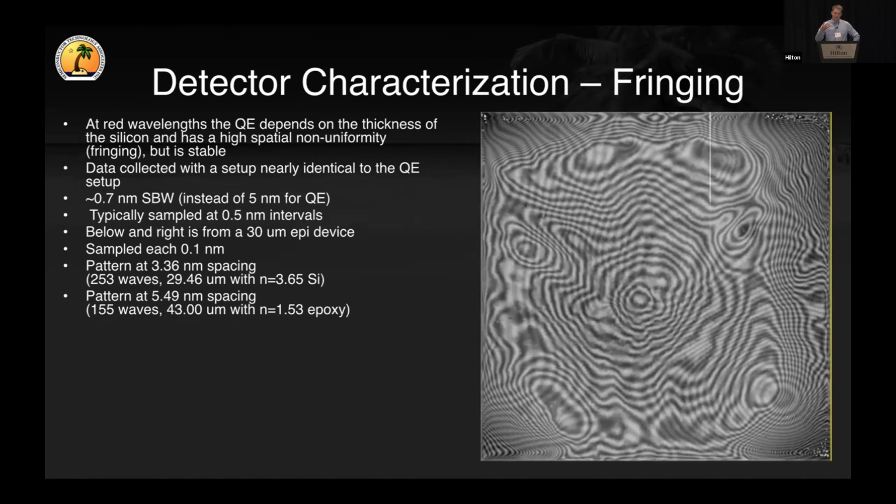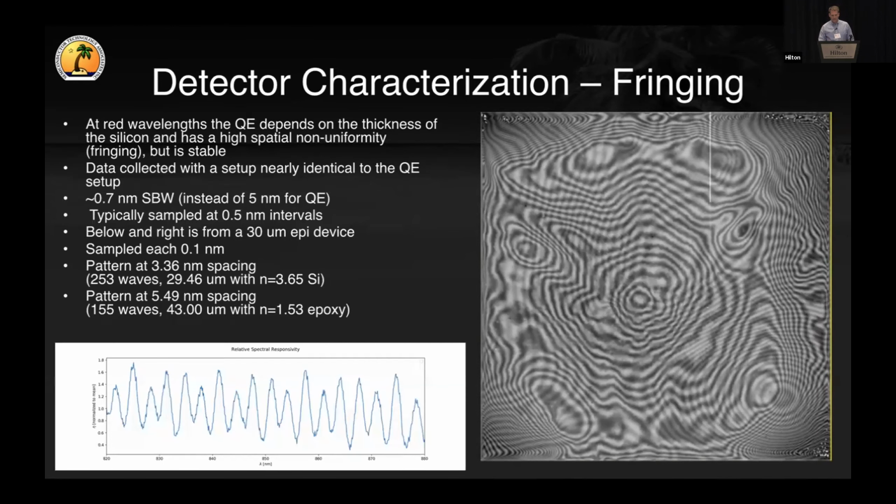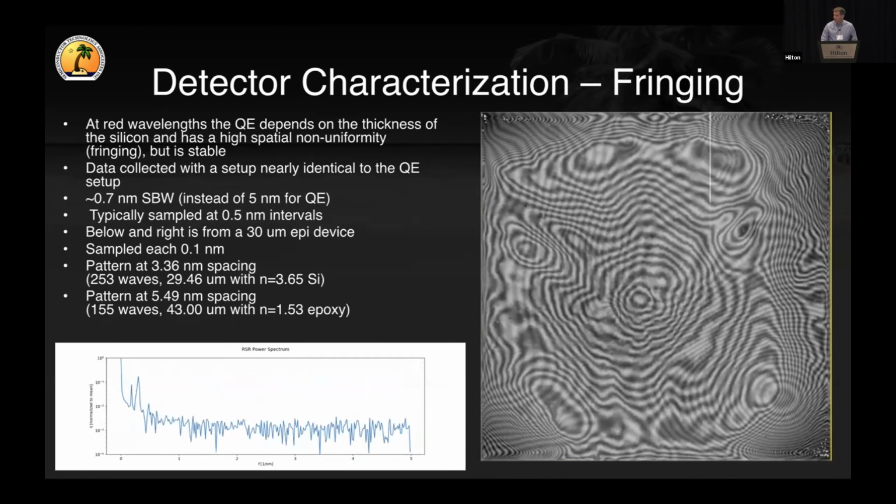And so I can change the fringing pattern and then measure it extremely well, and then measure the thickness of the CCD. Now that's fixed, and so in theory that could be used permanently in data. It doesn't change ever from the time of manufacture to the time of death of the CCD, which hopefully is very long into the future. And so that's one of the things that I would like to measure and use in a way that can help feed the data reduction process.